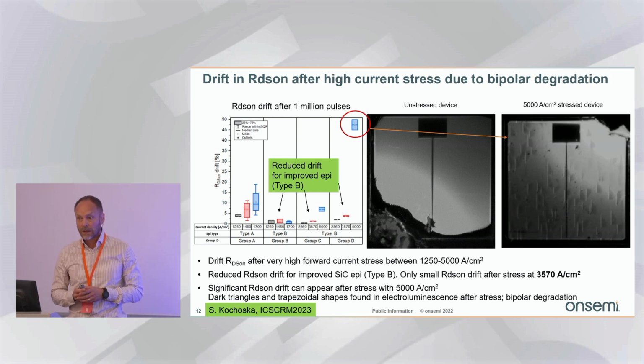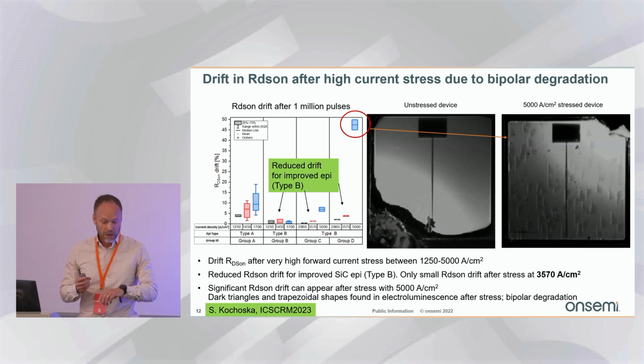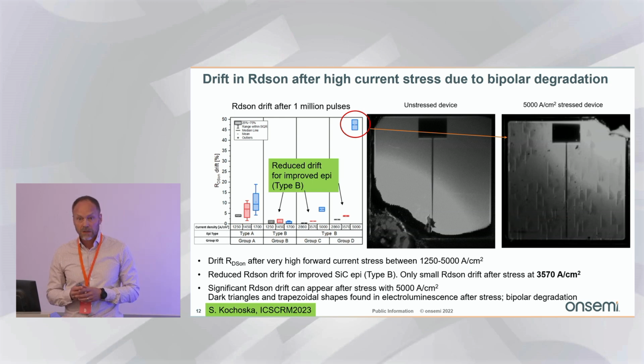And we examined that nothing strange had happened with the package, a wire bond or delamination, and then did some backside electroluminescence here. So you can see to the right that we see the stacking faults after very high current body diode stress, as proof of bipolar degradation. And in the center, you see the unstressed device, which has very homogeneous electroluminescence.